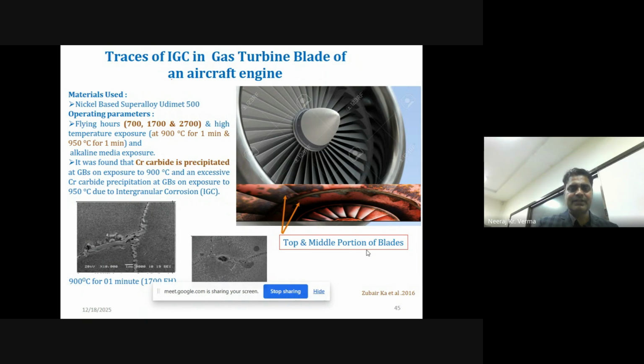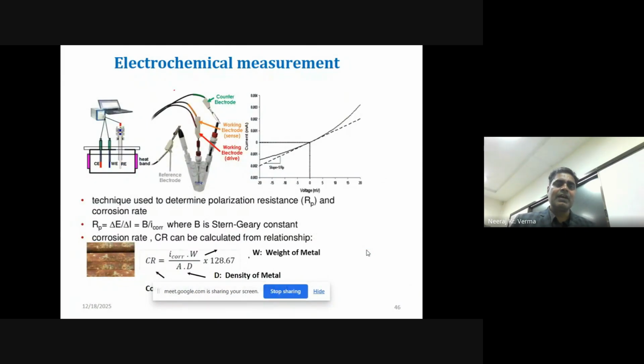These are some case studies related to IGC in turbine blades, which is due to carbide formation. This precipitate usually happens at a fixed temperature and is related to IGC, and whole components usually fail. Another topic is testing. I just previously discussed corrosion rate and how we can calculate it. The corrosion rate can be calculated in several ways. First is the weight loss method, which most people use, and this is a traditional method. But there are new techniques, the electrochemical techniques. On the basis of LPR, linear polarization resistance, we can also calculate the corrosion rate, as well as Rp, the polarization resistance of the samples.